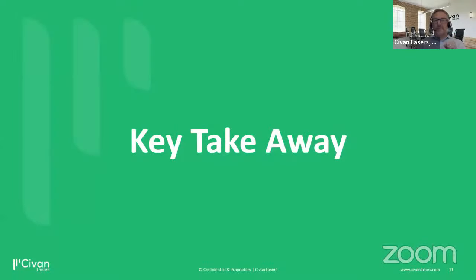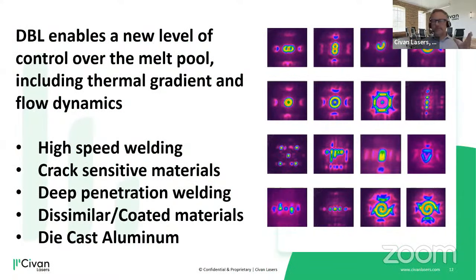So that's basically what I wanted to rush you through. Sorry for the speed. The key takeaway is the dynamic beam laser enables you to control the melt pool, the keyhole, so that you have the thermal gradients and the flow dynamics. That's something you have a direct control mechanism for. And that enables us to weld at higher speeds. We can weld crack-sensitive materials, something like 6000 series aluminum, for instance.